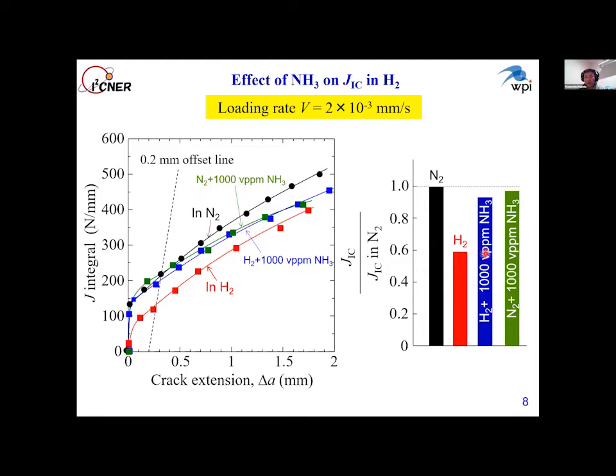In hydrogen plus ammonia, the fracture toughness value was almost the same as that in nitrogen. So we confirmed the mitigation by NH3. And in the nitrogen plus NH3 environment, the fracture toughness value was almost the same as that in nitrogen. So in this case, NH3 had no effect on the fracture toughness of this material under the given experimental conditions.